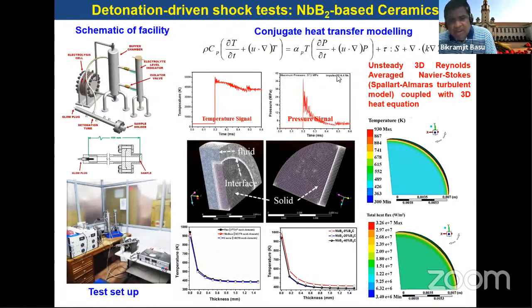We have also extended our niobium diboride work, and we have used a detonation-driven shock test. This is a little bit of a miniature model, not like the high-pressure shock tube model. While using this particular test facility, again at the Aerospace Engineering Department of IISc, we have modeled what the expected temperature and pressure would be at the shock material interface, and what the total heat flux will be.